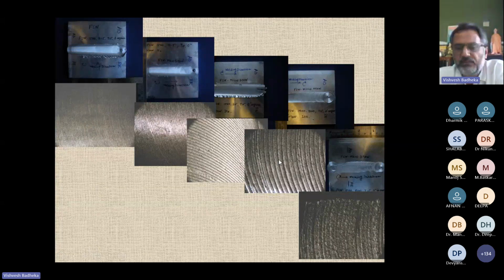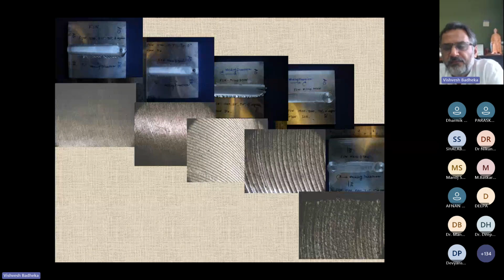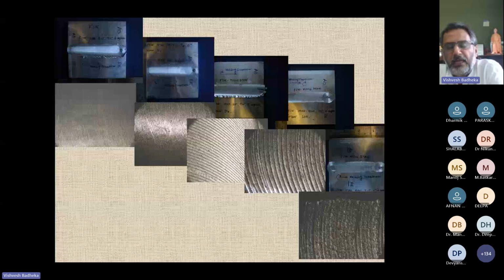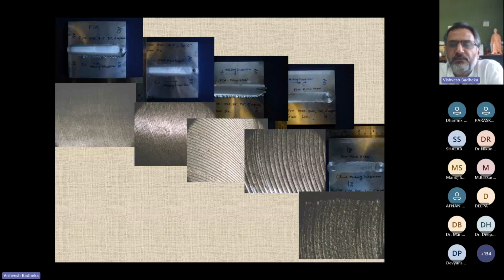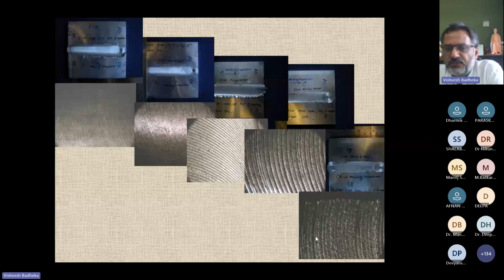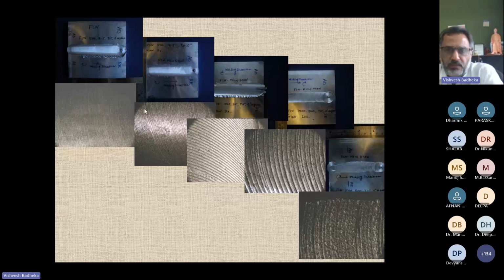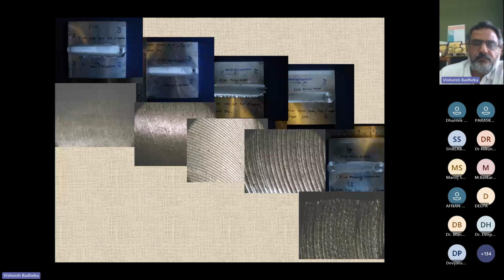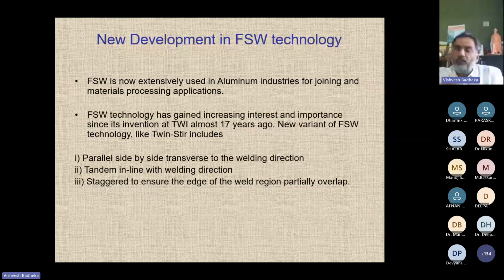Now you can see here, right? So even if you are applying assisted heating in a soft material like aluminum, you are able to increase the welding speed very high. With assisted heating, we were able to weld 500 millimeter per minute in friction stir welding. But the moment we go to 500 to 800 millimeter per minute, you can see there is an opening in the top surface, and you can see the rough surfaces also. So these are the in-house results. Even if you don't need assisted heating for a soft material, applying assisted heating mode will benefit you in terms of higher welding speed. So that was about assisted heating mode in friction stir welding.